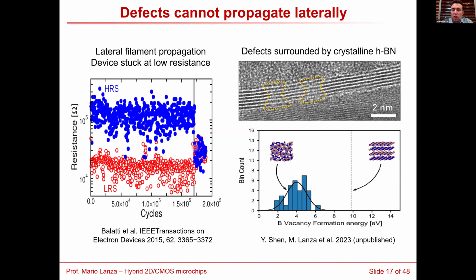The device has failed. So our idea of using a two-dimensional material grown by CVD is that it contains some local defects. You see some areas are perfectly layered, but some others look almost amorphous. The layered regions are very stable and you need a very high energy to form defects. But in the amorphous regions, you can form defects much more easily. So basically, you have a material where it's easy to make defects, confined in a nanoscale volume in between another where it is very difficult to make defects. And this, according to our initial idea, could make a confinement effect, and therefore maybe we can extend the life of this type of devices.